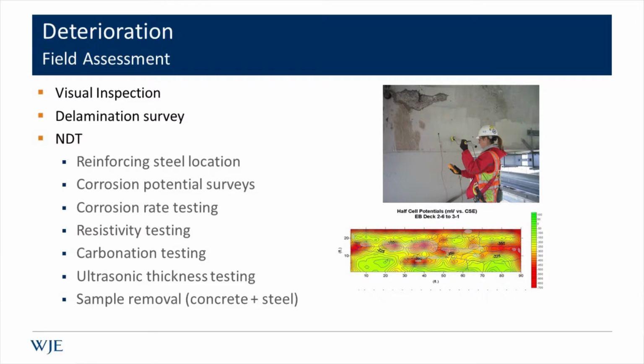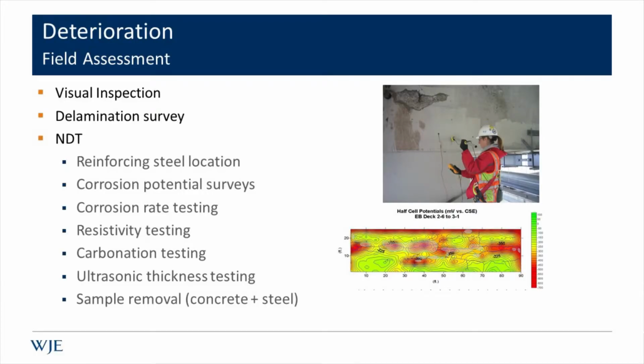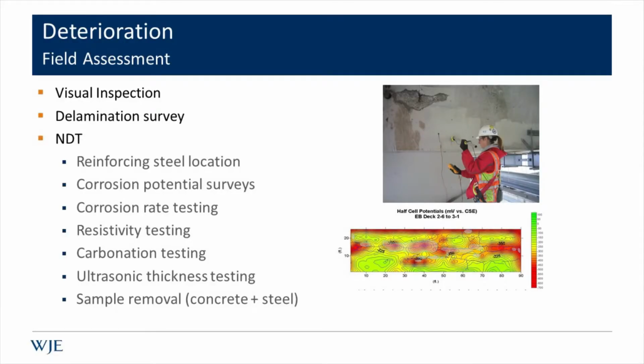So to assess the deterioration, really before you can develop repair strategies, the first thing you need to do is understand what it is you're trying to fight. And so our work started with a visual inspection of the bridge, where we're identifying all the deterioration that we can see. That's supplemented with a delamination survey, because I'm sure, as many of you know, the extent of damage is not always what you can see. The extent of delamination can be beyond that. There can also be areas that appear sound and are in fact delaminated. And then based on those results, we selected some study areas to do non-destructive testing, which included a host of the typical techniques from reinforcing steel location, corrosion rate testing and half-cell potential testing, resistivity testing, which was a consideration for the repairs, carbonation testing, and then steel thickness, ultrasonic testing, and core sample and steel sample removal for some strength testing.